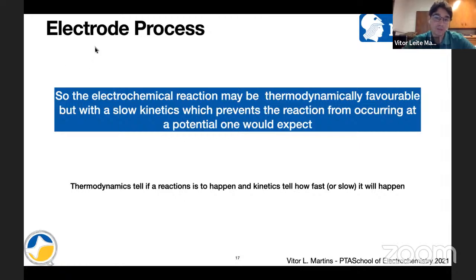The electrochemical reaction can be thermodynamically favorable. So the reaction should happen, but it has slow kinetics. So the reaction happens so slowly that we are not observing it. So the current will be really, really small. All right. So it's favorable to occur, but it occurs so slowly that we can't see it. You can't even measure it, because the current, as you will see later today and tomorrow, is the measurement of the rate of the reaction. So if we have slow kinetics for this reaction, we have a very small current to measure.